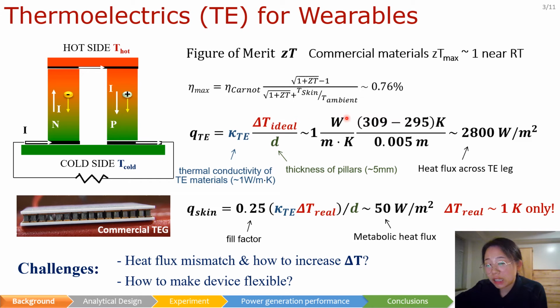Though the temperature difference between the skin and the ambient air can be up to 10 to 20 degrees C, the temperature difference across the thermoelectric materials that actually generates power is usually only 1 degree or less if we match the heat flux across the pillars to human skin metabolic heat. The mismatch between the two heat fluxes shown here limits the performance of flexible thermoelectric generators even made of state-of-the-art materials.